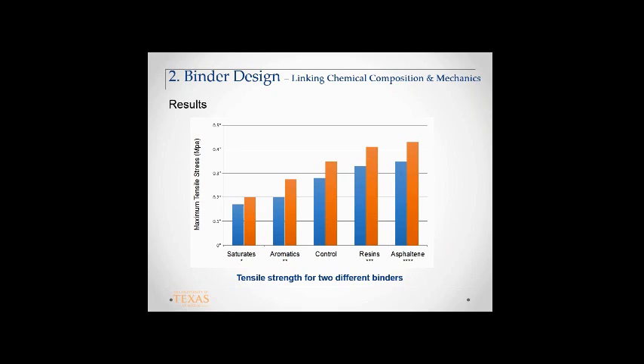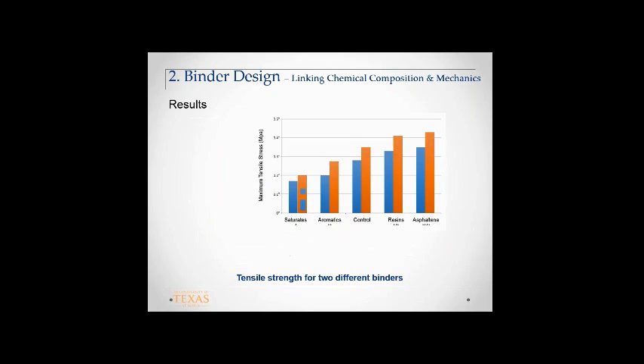Again, this is a very clean system, building blocks, idealized. But think of this from a practical viewpoint. We talk about RAP, recycled asphalt. We say that recycled asphalt will lead to more cracking. Recycled asphalt increases stiffness, but it also increases strength. So we shouldn't be jumping to conclusions saying you add more RAP, you get more cracking. Rather, we should be thinking that if I add more RAP, I'm increasing the stiffness of the system, but I'm also slightly increasing the strength, so it can take a little bit more before it cracks. So the question is, how do you balance the two? That is where we need to understand where the stiffness and strength balance out each other. So we take that.